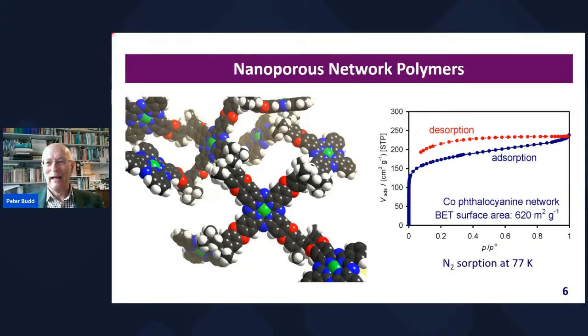and these nanoporous network polymers behave in much the same way. There is a slight difference in that the desorption behavior is a little bit different to the adsorption behavior. That's a hysteresis, but it's not the sort of hysteresis you get when you have a material with slightly larger pores, what are called mesopores, 2 to 50 nanometers, which is where another type of absorption occurs that involves capillary condensation. And in that case, the desorption curve will always close.